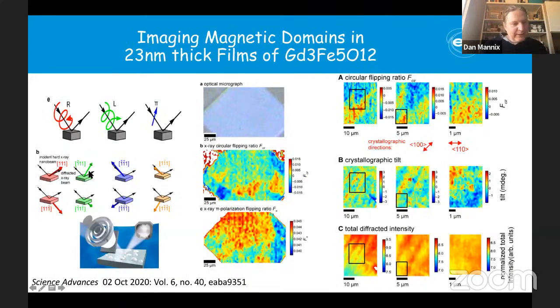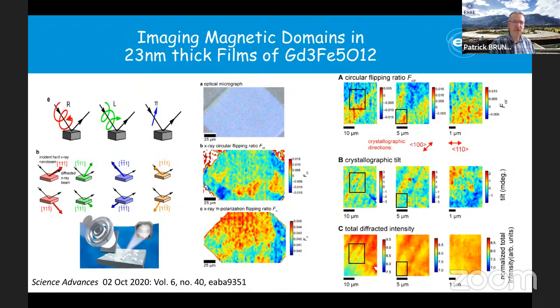Yeah, let's go back to what the domains look like. If we have this one sticking up along the 1, 1, 1, and then we have this 1, 1, 1 bar, the difference is basically the orientation along the film direction, right? It's a mirror image, but it's the same direction along the beam, just flipped up and down in the z-axis, you could say. You can't tell the difference between those two domains because you project on the cross product of wave vectors.